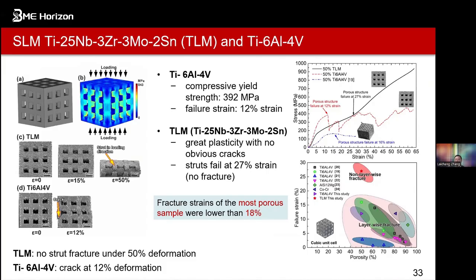That's why they can go further. So all these things, we can see for beta titanium alloys from these two types of beta titanium alloys. You can see there's no layer-wise crack. So for the beta titanium alloys, that's a non-layer-wise fracture. So the structure is quite good, and also the material.